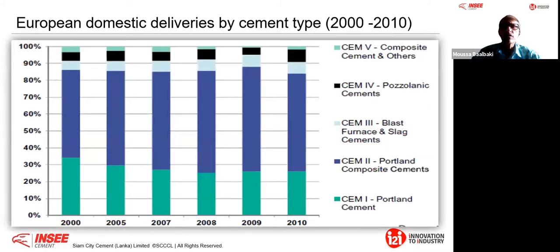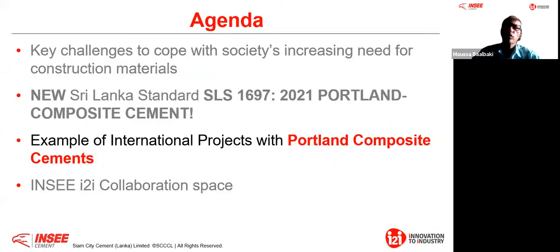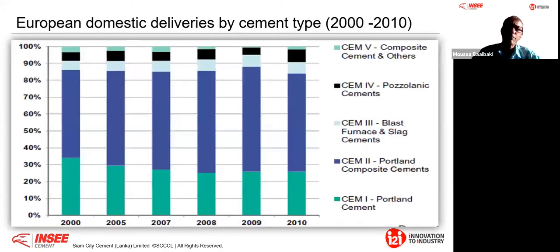Now, giving you some examples of Portland composite cement at international level. I have presented this slide very often, just to show, for example, what the European domestic delivery in cement was, let's say, 10 years back. You see in this graphic, more than 50% is Portland composite cement. On top of that, you have pozzolanic CEM4, you also have CEM3, these are blast furnace slag cements, where the slag is above 60%.